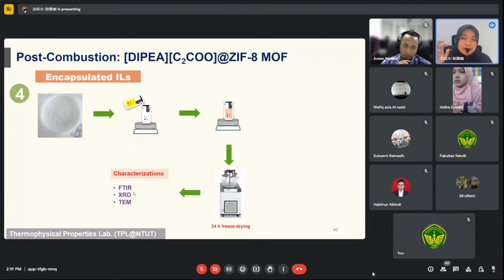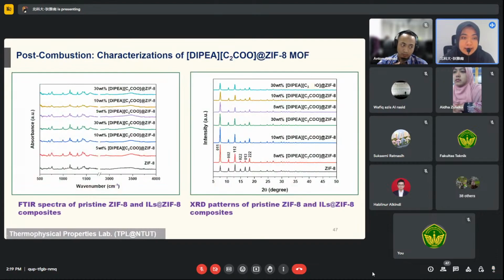For the XRD, we can check the crystallization. For the FTIR, we can check the compound that is probably unknown, because here we would like to confirm. Actually, this is just based on confirmation: is the ionic liquid and the ZIF-8 totally inside this material or not, or do they form another chemical? So basically, this is one of the FTIR spectra and the XRD, to compare with different mass fractions of the ionic liquid.